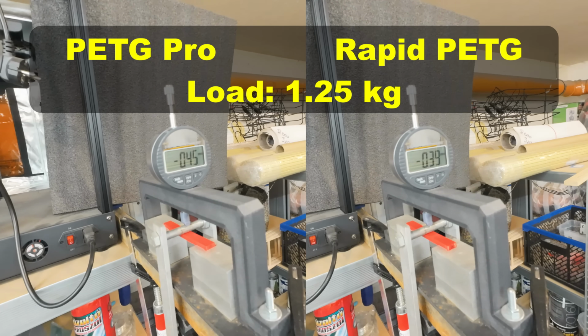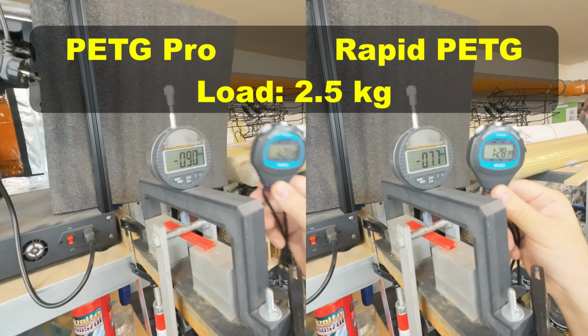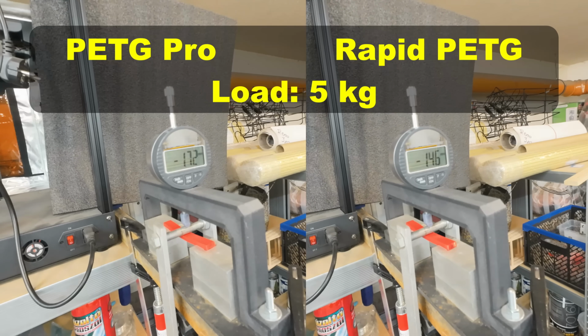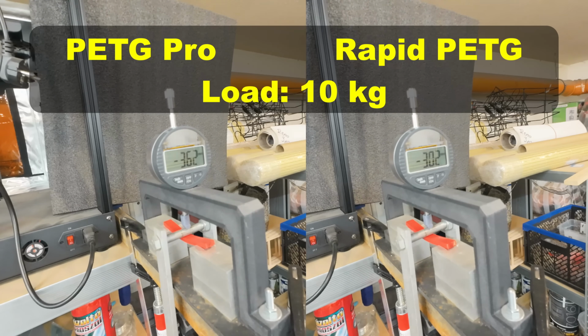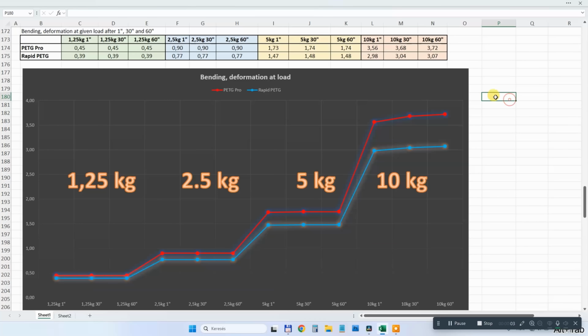3-point bending test. Distance between supports is 50 mm, and I'm measuring the deformation after 1, 30 and 60 seconds. This is the deformation under 5 kilograms. And this is under 10 kilograms, and very minimal additional deformation during this 1 minute. Smaller values are better, less deformation, and here the rapid PETG is again better, but what is interesting to notice, under 10 kilograms we have less deformation during the time compared to the PETG Pro. This is some kind of creeping, but I have a whole separate test for this.